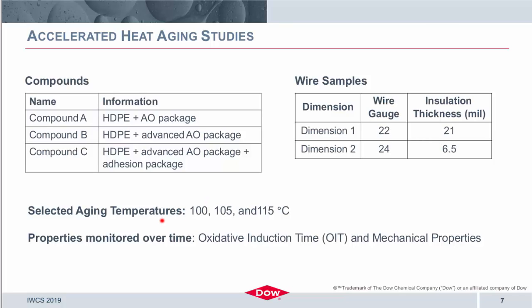We selected 3 different temperatures to run the accelerated aging conditions, those being 100, 105, and 115 degrees Celsius. And as I've mentioned, we monitored the oxidative induction time and the mechanical properties after aging.